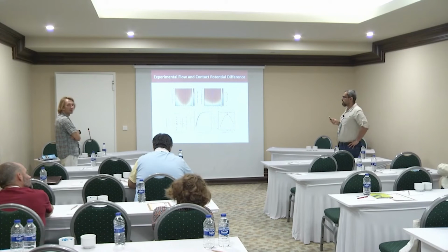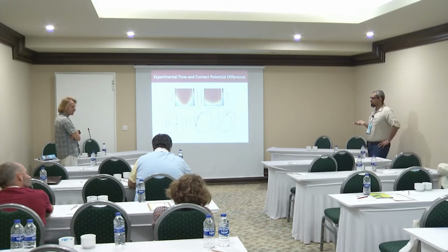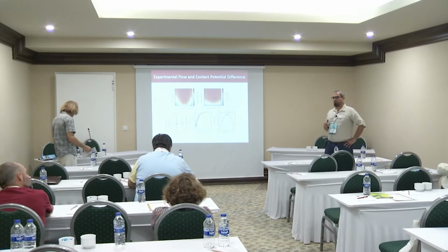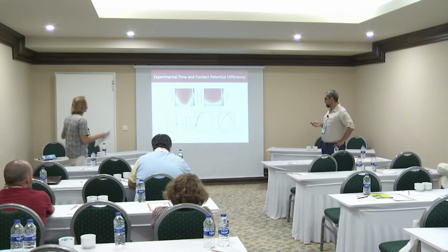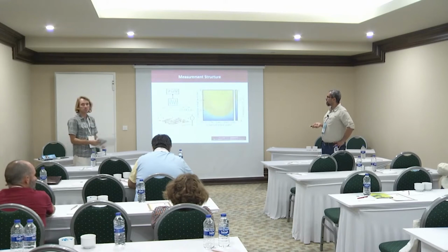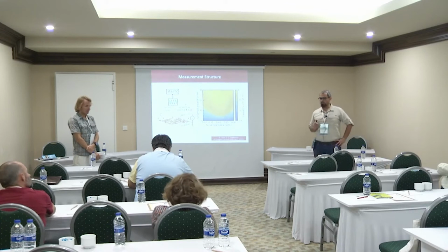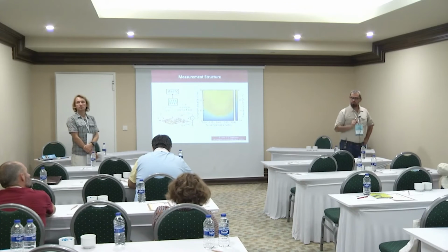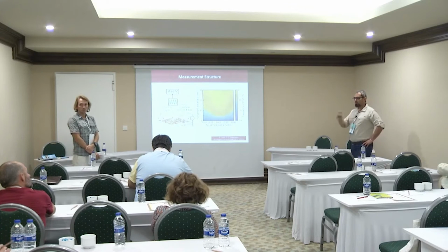And on top of that, in order to make sure that we don't have any adsorbates on our tip or on the surface when we do these potential measurements, we looked at the energy dissipation maps of the surface, because if there are more adsorbates on the surface, the energy dissipation would have increased, and this would show up in the signal that we drive our cantilever. So this is actually a property that we can physically measure, and we measured it, and we didn't see any statistical difference when we did cyclic measurements and over the course of the measurements.